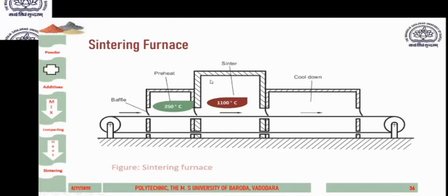Generally the time for sintering goes up to a day or half a day or so, and this material, when it reaches the center part of the furnace, is generally stationary. Once the sintering time cycle is completed, the part is moved to another insulated part where it is cooled under controlled conditions, so that products of oxidation and corrosion do not affect the component that has been sintered here. So this is the process cycle in sintering.